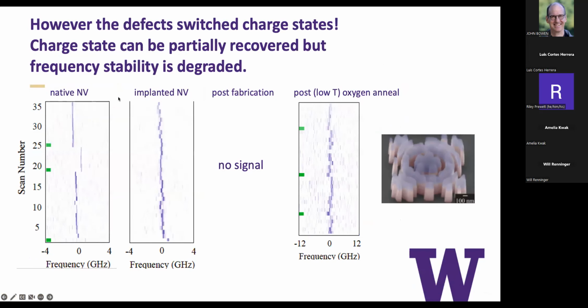But the NV centers that were in this device weren't the best, but they were actually pretty good. So this is what they looked like after they were implanted. This is, to us, pretty hopeful that we would be able to stabilize at this level. After we fabricated these devices, there was no signal at all from the NV centers anymore. And that was because simply the exposure to the plasma that needed to be used to etch the gallium phosphide, which did not etch into the diamond, left the nitrogen vacancy center in the wrong charge state.